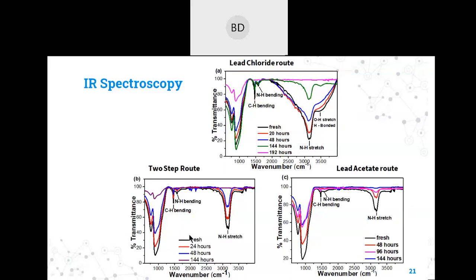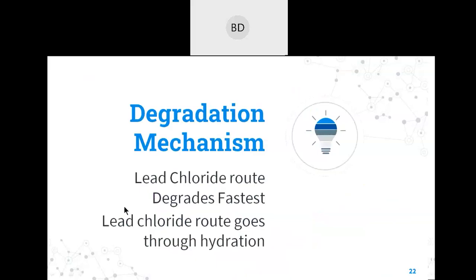And also the IR spectroscopy favors the same degradation process. This lead chloride route degrades faster and these two comparatively slower. So from all these observations, we understood that the lead chloride route is degrading much faster and it goes through a hydration mechanism as compared to the counterpart processes. So now the question is why it is happening? Why the lead chloride route is going some different way, whereas the other two routes are going some other way, although the perovskite is same in both the processes.